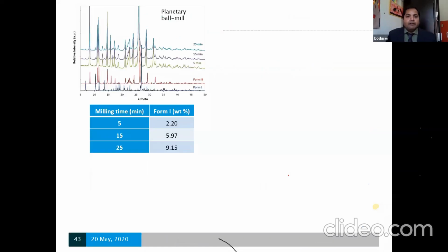What happened was, when we used the planetary ball mill, which is more energy intensive, by the first 15 minutes you could see form 2 has converted into form 1. And by 25 minutes, you could see more of form 1 coming. At each stage, even where we are not able to see anything here, there is also a minute quantity of phase transformation that has occurred by 5 minutes only. We have done again extensive Rietveld analysis of each of these powder patterns to see to what extent this conversion has happened. By 5 minutes, you could see 2% of form 1 has formed. And similarly for the other two extended times, there is an increase in formation of metastable form 1.